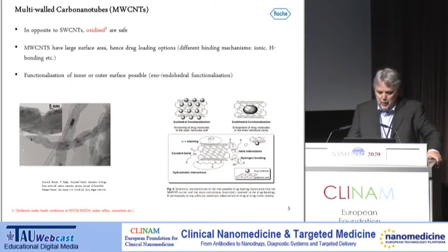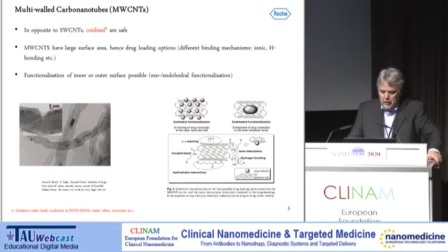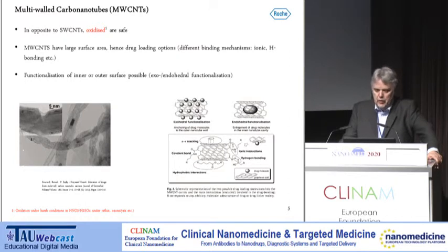For the multi-walled carbon nanotubes, I'm focusing here on the oxidized carbon nanotubes, and you have seen this example nicely from the regulatory representative from China, this gadolinium compound. It's more or less related to the fullerenes, which had huge interest 20 to 30 years ago. Typically they are toxic for medical applications, but if they are oxidized under harsh conditions with sulfuric acid and nitric acid or with ozonolysis, then you can have biocompatible carbon nanotubes. And here the multi-walled carbon nanotubes are of interest.